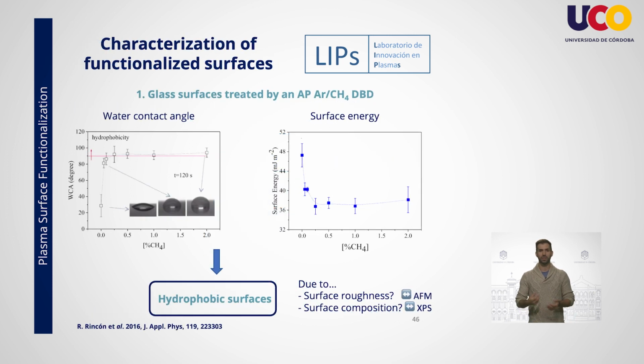In this first work, the aim is to analyze the effect of an argon-methane dielectric barrier discharge plasma on a glass surface. For this purpose, first, the water contact angle was measured as a function of the percentage of methane introduced into the gas mixture. It was found that the introduction of methane induced a change in the wettability of the samples. For methane concentrations about 0.25%, the surface showed a hydrophobic behavior, which is consistent with a decrease in surface free energy. We wanted to understand the phenomenon causing this behavior.